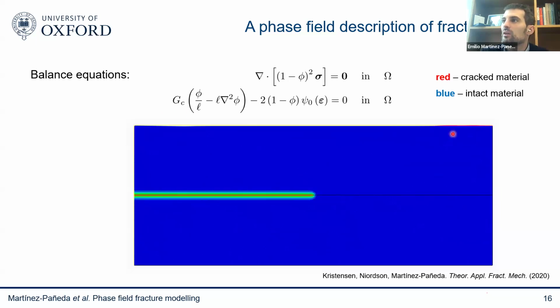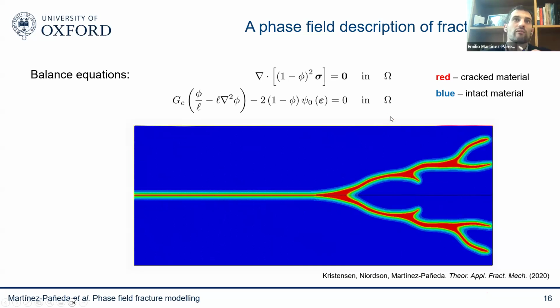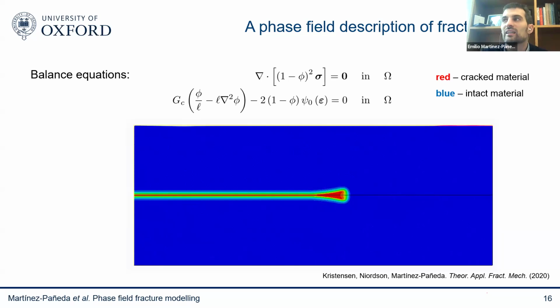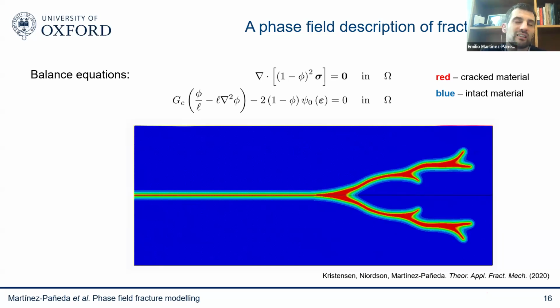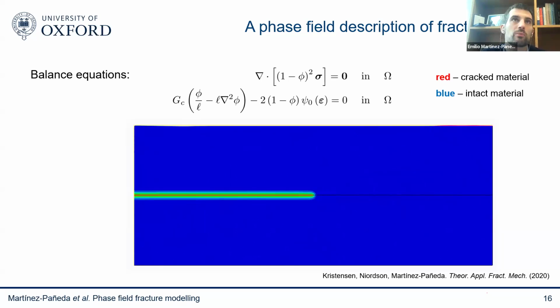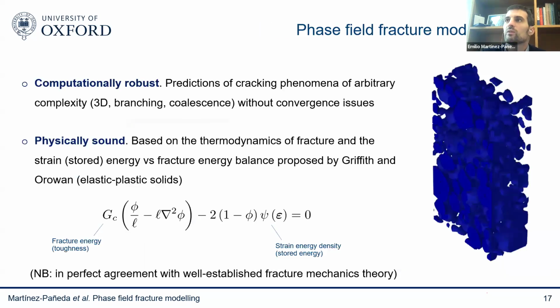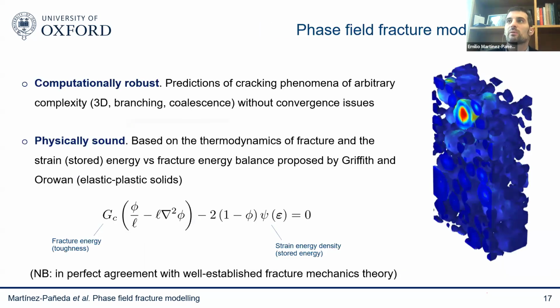You can see here, for example, crack branching due to the application of a dynamic load. So here you see, because of the wave interaction, you see that the cracks are branching. And this I can capture on my original finite element mesh and without any convergence problems. So again, the reason why the method is so popular is because it's computationally robust. We can predict complex things without convergence issues. As you can imagine, fracture mechanics is challenging from a convergence perspective. You go from something that is carrying load to something that fails catastrophically where the carrying capacity is lost.